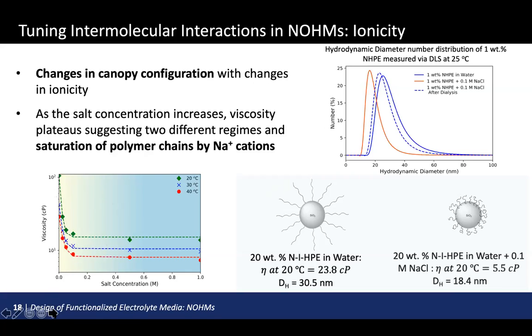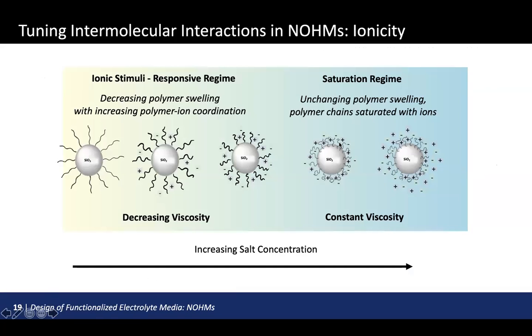So based on this, our current hypothesis is shown here. We see from these studies that it seems the polymer chains are interacting with these ions, which leads to their configuration changing and them collapsing. And we therefore see this decrease in the viscosity. And eventually, if we continue to add salt ions, because these polymers are saturated, this viscosity will no longer change and remain constant.